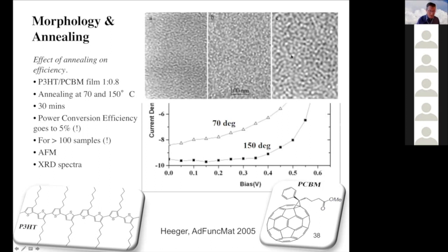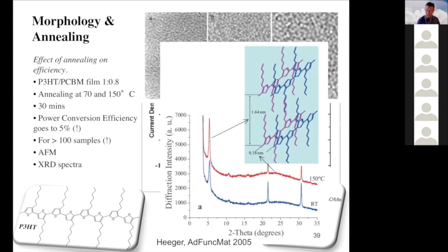So the fullerene phase and the polymer phase, they are better separated. And annealing also improves the crystallinity of the domains. That is shown here. So this is X-ray diffraction. The increase of this peak, this peak becomes stronger. Now that implies that there's more crystalline region, because in X-ray diffraction, only the crystalline regions give these sharp peaks.